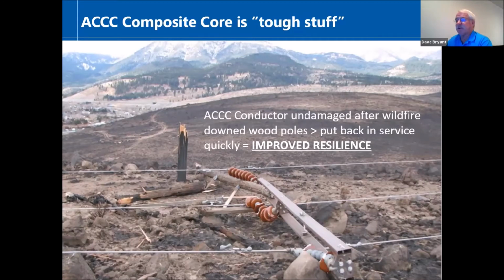They used steel cross arms, new insulators, and the ACCC conductor. The ability to increase capacity allowed them to shut down spinning reserve down in Carson City. This line went from Reno in the north down to Carson City, the capital of Nevada, and they were able to save $9 million by shutting down a spinning reserve. Now, this line was out of service for 4 days because of the fire, but fortunately the conductor wasn't damaged. They were able to come in, replace the wood uprights, use a helicopter to replace the insulator, and lift the conductor back in service.